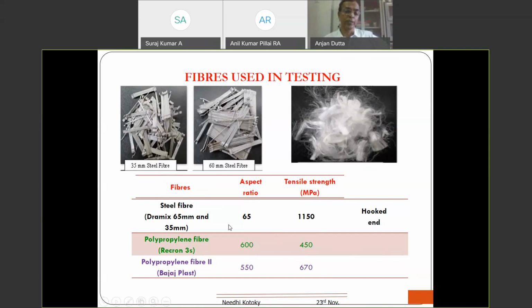The aspect ratios are quite different. When you look at the aspect ratio of steel fiber, this is 65. We call the steel fiber a microfiber and the polypropylene a macrofiber. Now what happens when they are mixed in concrete and a concrete specimen is loaded? Once it is loaded, eventually it starts developing cracks. Initially there will be small cracks, or micro cracks. Whenever there are micro cracks, the microfibers will play a role there and immediately arrest those micro cracks, because eventually those micro cracks coalesce and develop a macro crack, and finally it leads to a major crack and collapse.